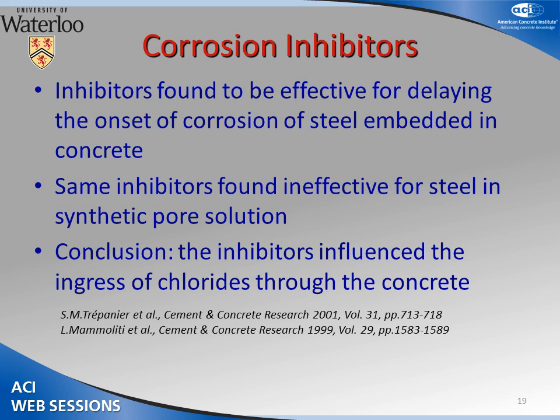However, it did not have much effect on the corrosion rate after initiation of corrosion, and if you tested the steel in pore solution containing inhibitors, then there was very, very little effect, if any. So this suggests, of course, that unlike the hypotheses of the day, the inhibitors were not influencing the passive film on the steel, but influencing the ingress of the chlorides into the concrete.